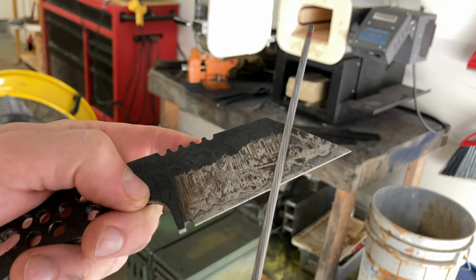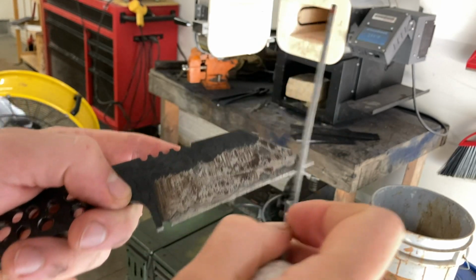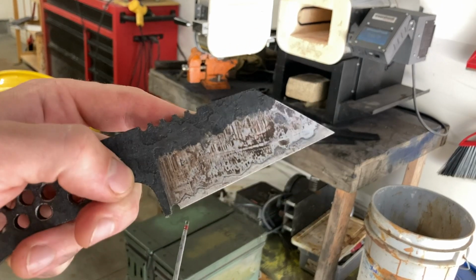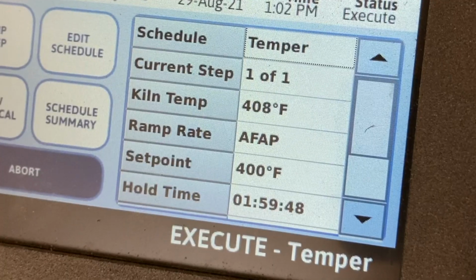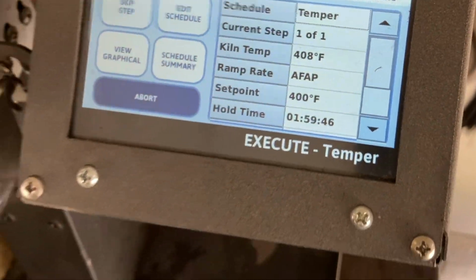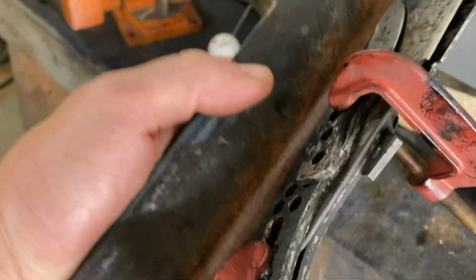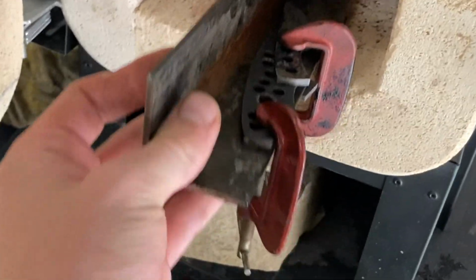After quenching, I like doing a quick hardness test using one of my chainsaw files, and since it's just skating across the edge without biting in, that's a good indication it's nice and hard. And then in order to bring some toughness back into the steel, I'm going to temper the knife at 400 degrees for 2 hours and then do 2 cycles of that with cooling the blade in between.